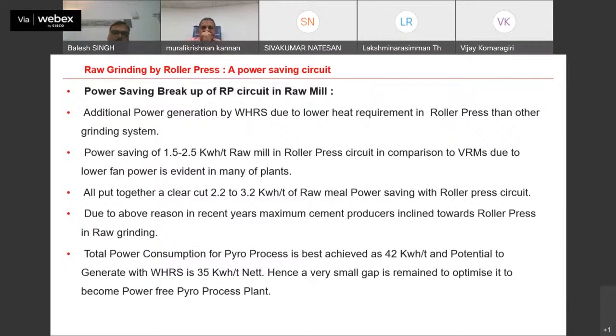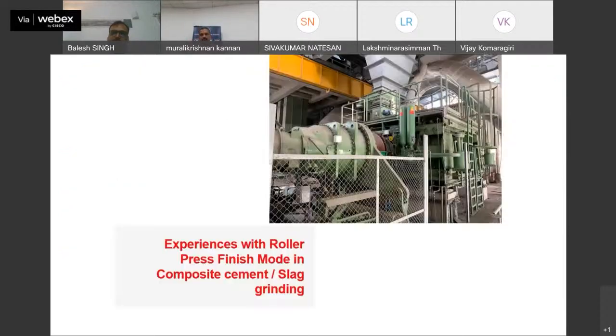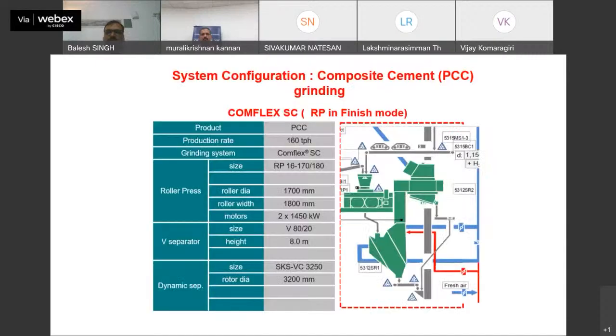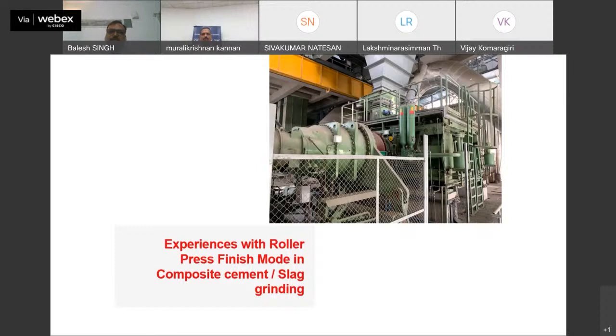Total power consumption for the pyro process, I already explained previously, there is hardly a few units difference that comes from power generation and power utilization. So this is a very interesting experience with the roll press in finish mode in composite cement and slag grind. Earlier it was assumed that in roll press the composite cement grinding may not be feasible or may not be economic, but definitely this is being done and it is already running successfully for many years in many places.